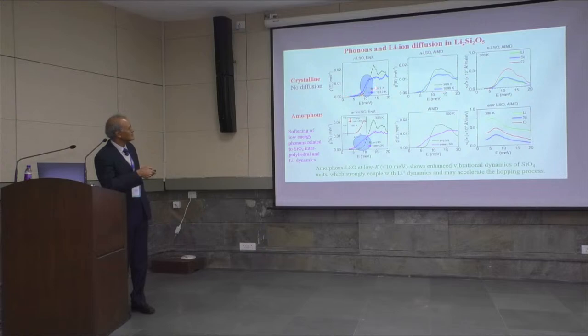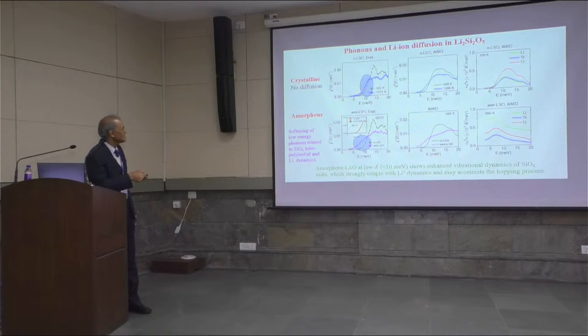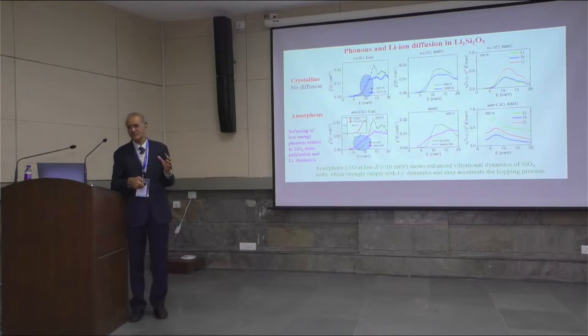And here, at room temperature, you have a certain density of states, and then as the temperature is increased, there is a shift to lower energies in this material. This is a marginal amount. Now, if you go to the amorphous structure, then there is a lot more shift and a broadening. So, qualitatively, one can associate this with the softening of these low energy phonons, and we can find out from theoretical calculations what is involved in these phonons. What kind of atomic dynamics or atomic motions are involved?